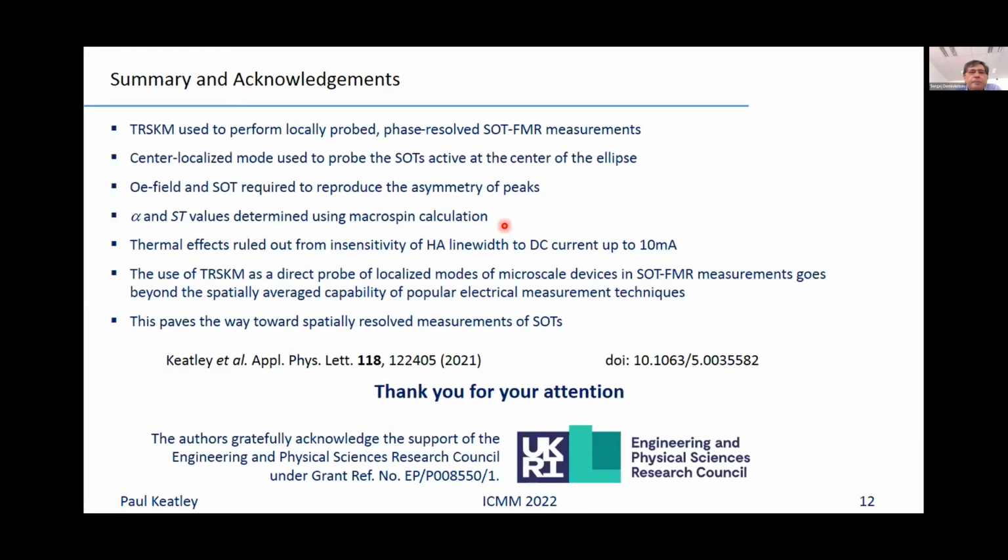Yeah, hi Sergey, thanks for the question. So the beam is actually blocked as it goes back to the detector. So the spot on the sample is actually the same as in the polar case. It's just that you reject half of the beam, so any polarization rotation in the beam still has a polar Kerr component, but if you're making an in-plane hysteresis loop measurement, you don't expect an out-of-plane component for a static measurement. So to answer simply, yes, the spot size is the same.